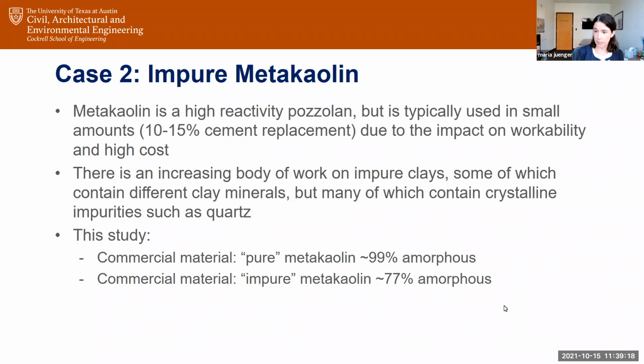Another example similarly is clay. So clay is abundant around the world, and typically in concrete mixtures, we've used a very purified form of kaolinite clay that's been heated called metakaolin. We typically use it in really small amounts because it negatively impacts the workability and can have a really, really high cost. So we're using it in very, very tiny amounts. But there's an increased interest in using clays at greater amounts as substitutes for fly ash, in which case you can start looking at clays that are less pure and what the impacts of those materials are in the system.